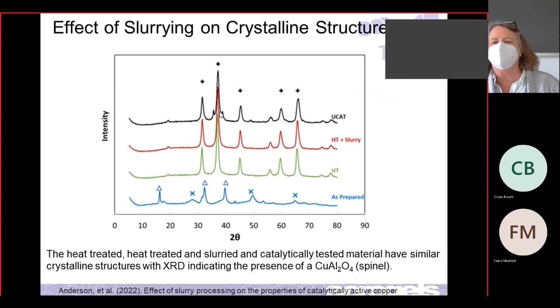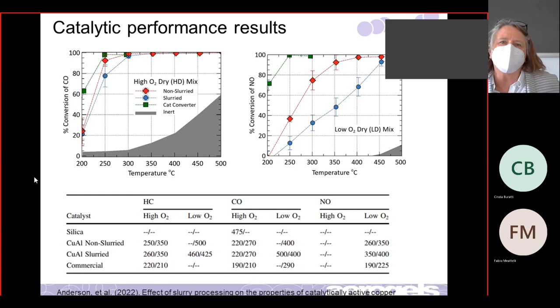But the big thing was the catalytic performance results. If we look at conversion of carbon monoxide versus temperature, the red is the regular stuff like I showed you before, and the blue is the slurried. Within our uncertainty, they're basically the same. We went from CO 220 light off to 220 light off, didn't change. Hydrocarbons was similar, maybe a little bit higher with the slurried. These numbers represent light off.